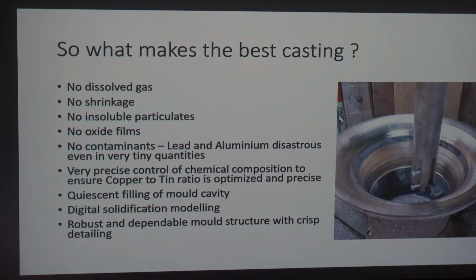And then the other thing is the mould structures themselves. These days, moulding materials are much more clever. There are lots of different sands we can use. We can use chromite sands, zircon sands, silica sands, and all sorts of polymer-based binders which are very much more robust than the traditional ways that the sands have been used in the past. And it can be recycled these days as well. They're engineered so they can be recycled too.